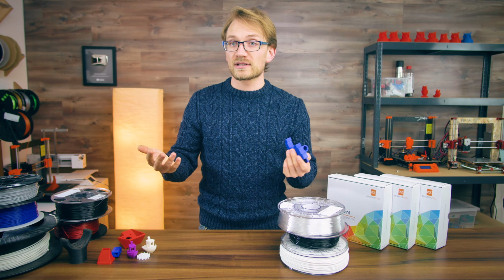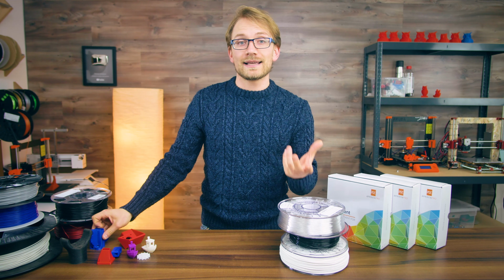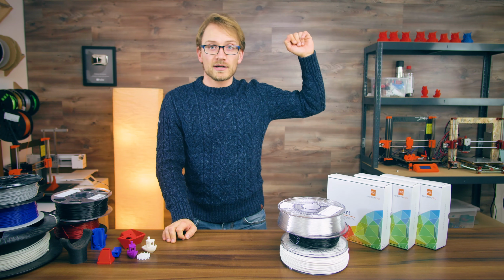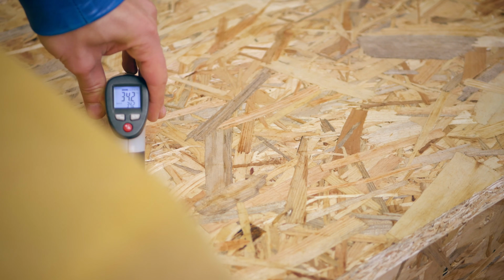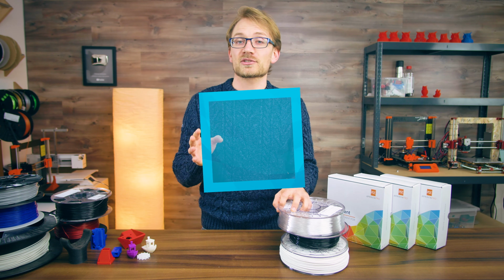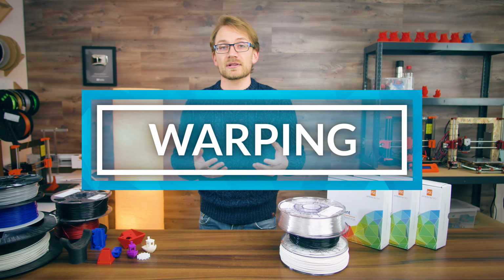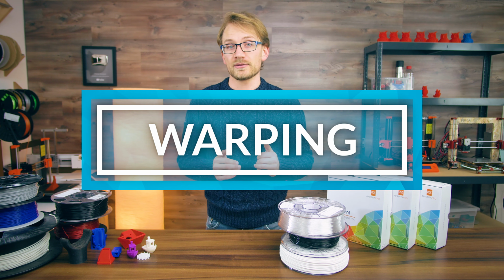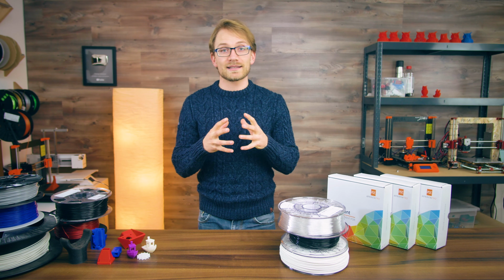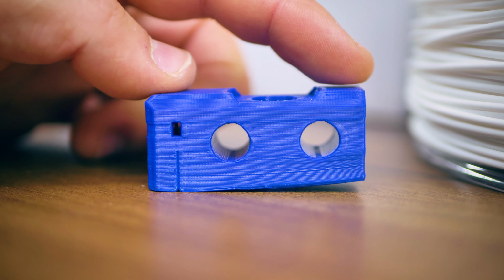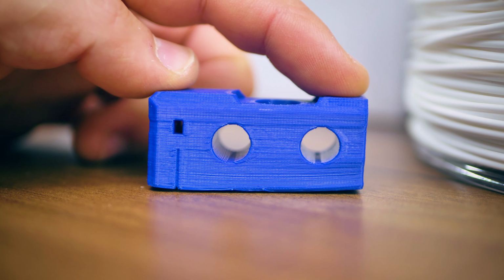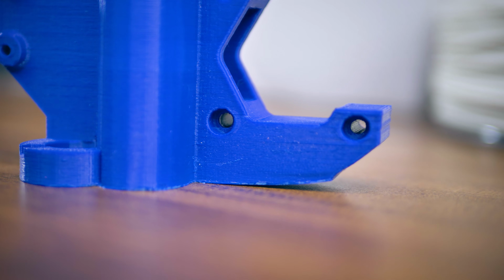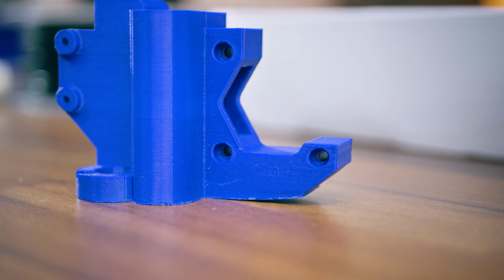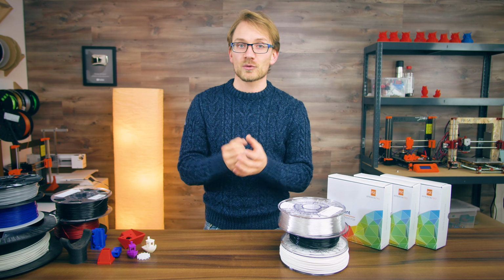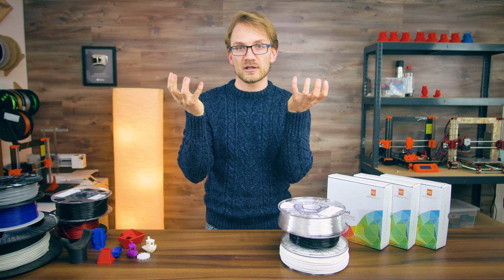I've moved on to printing any ABS-likes exclusively in an enclosed chamber, video here. The prints come out much stronger and I don't have to worry about warping that much anymore. Yes, the warping. As we touched on in the last video on PLA, having a material that stays soft longer as it cools down will also give it less of a chance to contract and actually warp your part. Because molten printed ABS is already pretty hard when it has cooled down to about 100 degrees. As it cools down further to room temperature, it can't stretch to make up for the thermal shrinkage as easily anymore, so it will want to pull up your already printed part like a dish.